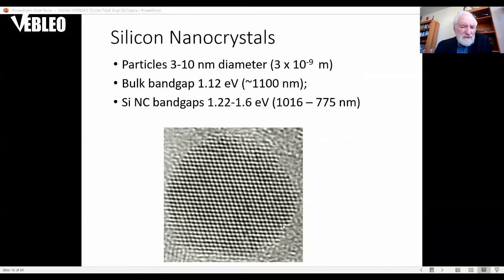And this just shows a silicon nanocrystal. This one's about 4 nanometers in diameter, and under TEM you can actually see the atoms of silicon here in a very nice TEM photograph of a silicon nanocrystal.